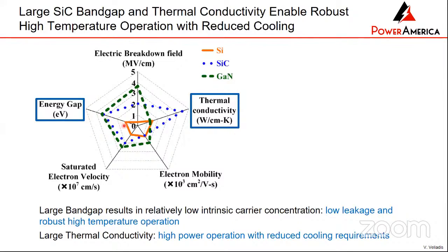And of course, the higher energy band gap of silicon carbide and GaN, as shown here, means that at room temperature, you have very few thermally generated carriers. And that means that you have very low leakage current and also that you can operate at higher temperatures.